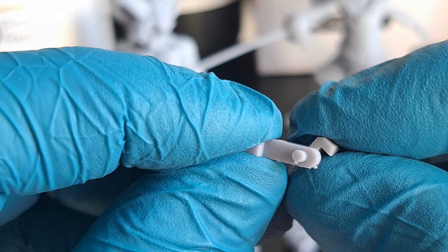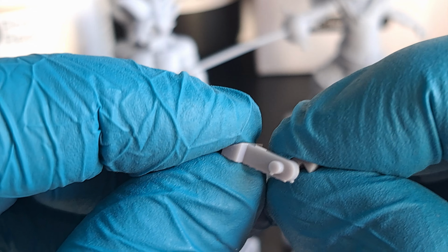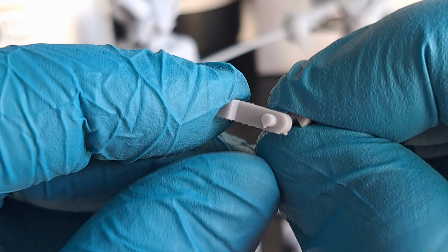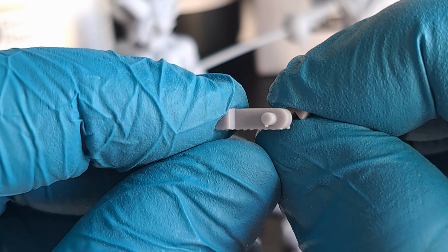This flipper part is about 1.6 mm thick, and I twisted it. Instead of failing suddenly, it resisted the twist and took way more force than I expected. This resin resists twisting because the layers are bonded so well. For small, high-stress parts like couplers, that makes a big difference.